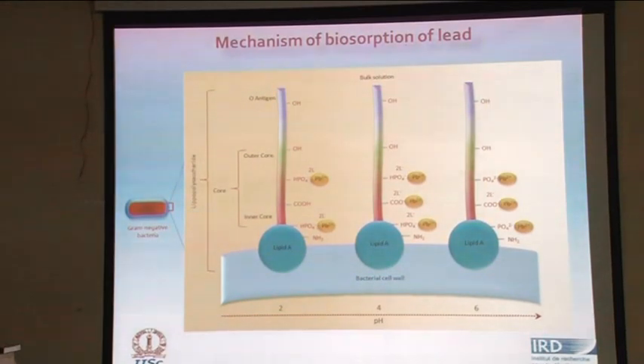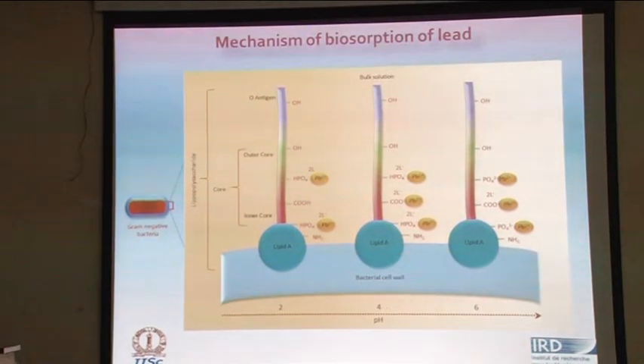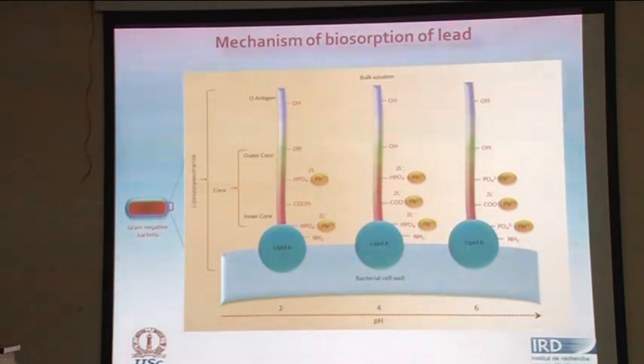We also did some work on the use of this for electrochemical studies. I'll come to that a little later. But what you see here is the mechanism of the bacterial adhesion to the metal ions. In the bacterial cell wall, you have various lipids, which have some functional groups like the carboxyl group, and you have the phosphate. These are potential sites for binding the metal. And the ionization of phosphate, as we all know, is again a function of pH. If you want complete ionization, you have to go to higher pH values, as you can see here.